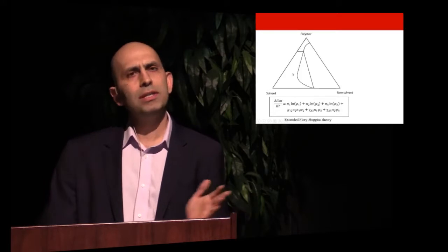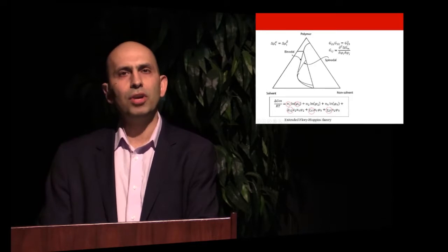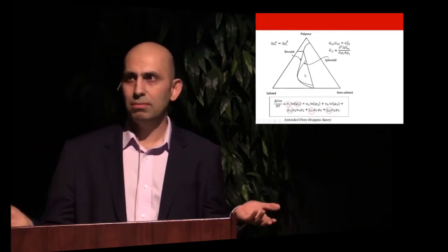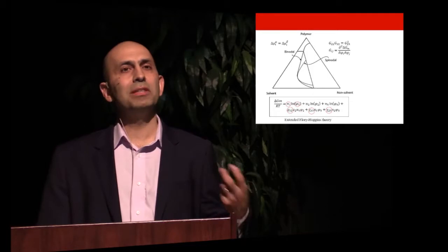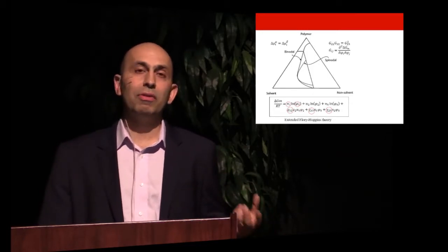A little bit about the mathematics of this. The term here is the Gibbs energy of mixing. Here you have different components, and here you have that phase diagram. When we start from a homogeneous solution, we are here at the composition of solvent and polymer, and that composition is the equilibrium and happy composition, if you will. If you force this solution out of equilibrium, it is going to pass that boundary, and we end up with a two-phase scenario. That two-phase scenario is what we call a membrane, because soon after you extract the solvent, the excess material left in the void, you will remain with a porous matrix.